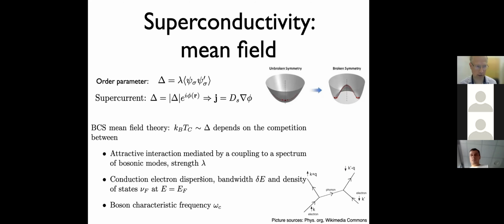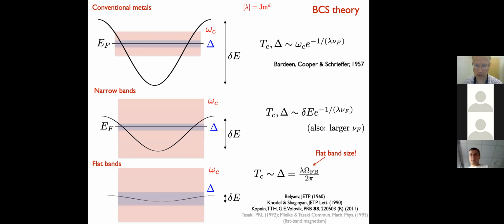One can study the mean field delta in these various systems and study how it behaves with respect to these parameters. First one can start from conventional metals, where the bandwidth is the largest of these energies. Then the bosonic energy or frequency is below that, and superconductivity lives on an even much smaller scale. In this case, we have the usual BCS result where delta is proportional to this cutoff frequency times the exponential containing the coupling strength and the density of states.